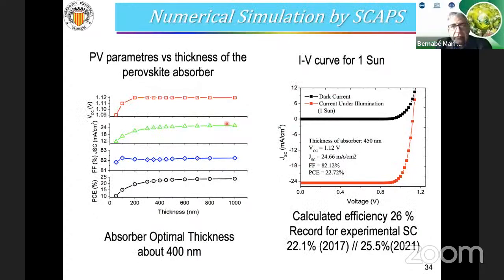Well, we have also prepared this kind of samples and made numerical simulation by SCAPS in order to know what are the best conditions. So the first thing we obtained was that the optimal thickness for the absorber is about 400 nanometers. And well, in 2017, we calculated an efficiency of about 26%. And this fits very well with the record of experimental solar cells, which was 22% in 2017 or 25.5% right now. So our calculations are quite exact.